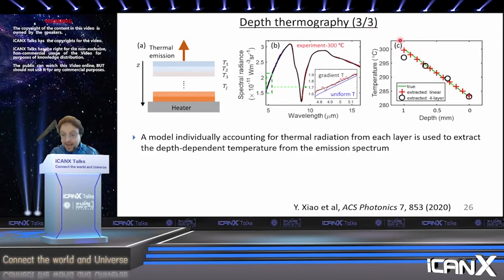So this green line over here is what we expected the temperature to be. In this case, we expect it to be just a simple linear drop, really just Fourier's law of thermal conduction. The thermal radiation actually only has a relatively small component inside the material, and therefore we expect the temperature versus depth to just be a straight line. And actually it is. So if we assume a linear relationship, we can extract this line almost perfectly. And if we don't assume a linear relationship, if we just let these temperatures float arbitrarily and we fit them individually, we get this relationship that also falls on this line, although it's not exactly perfect. Part of this is some experimental and computation error, and part of this is because in reality the temperature as a function of depth is not exactly linear in this situation either, and so we might be capturing some of that just a little bit.